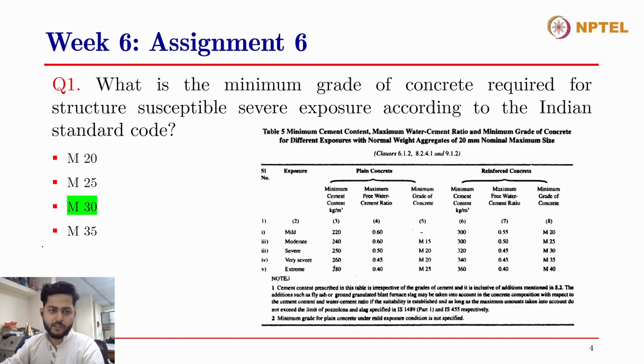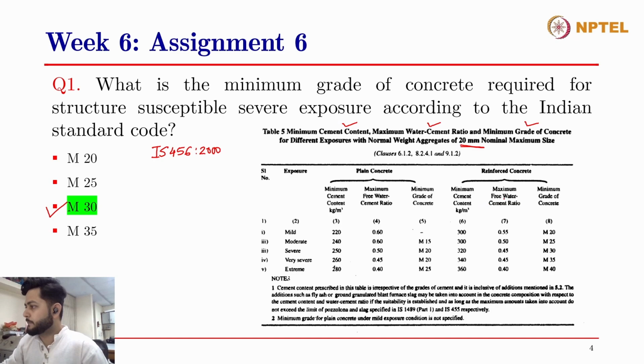All right. The correct answer to this question is M30 grade concrete. And this is the table 5 of the Indian Standard IS 456 2000. And the table 5 tells us about the minimum cement content, the maximum water to cement ratio, and minimum grade of concrete for different exposures of normal weight aggregates of 20 mm nominal maximum size. So 20 mm is the maximum size of aggregates allowed for the application of this table number 5. And the exposure conditions are given from mild till extreme conditions. And all these three parameters, the minimum cement content, maximum free water to cement ratio, and the minimum grade of concrete, have been listed out for the plain concrete, meaning PCC, and reinforced cement concrete, RCC.